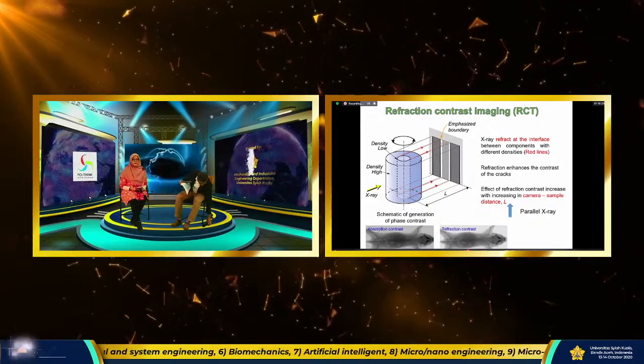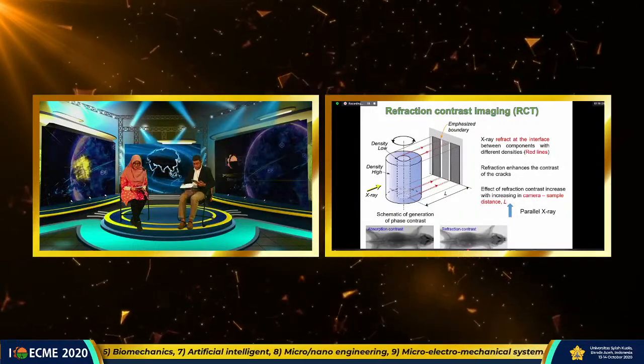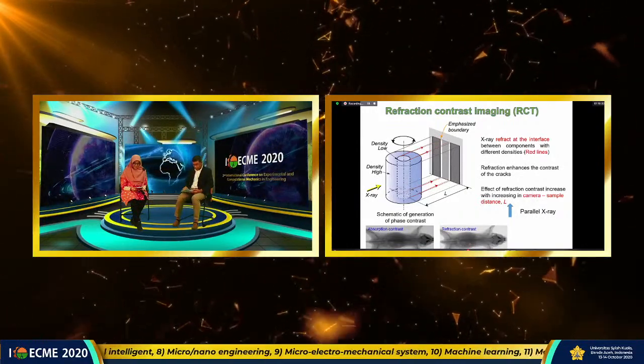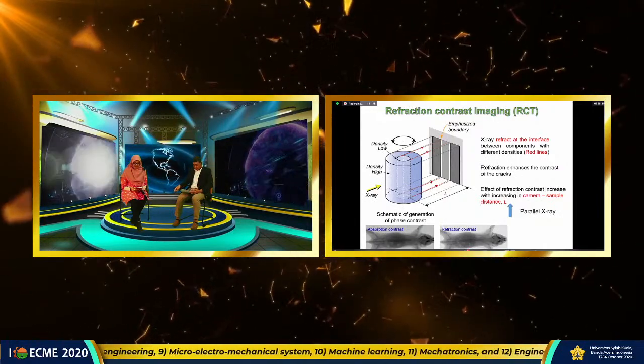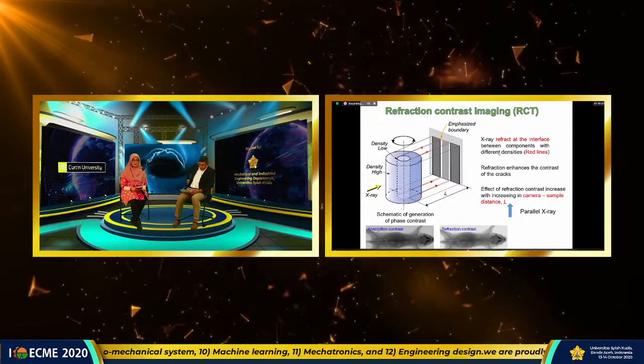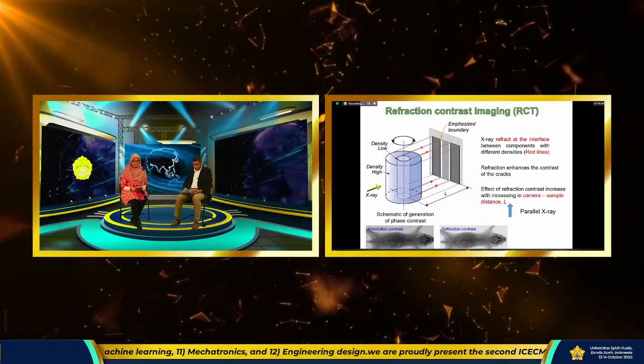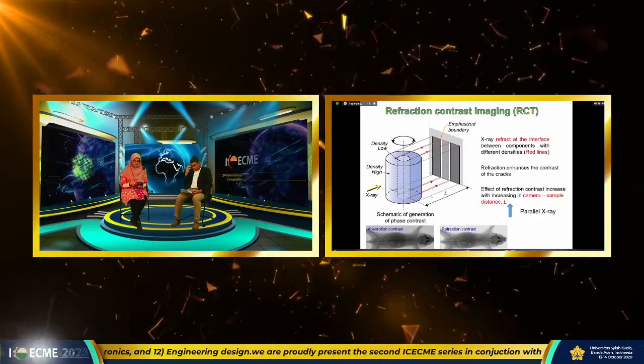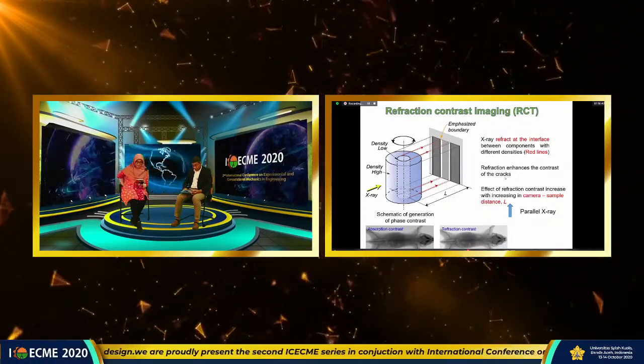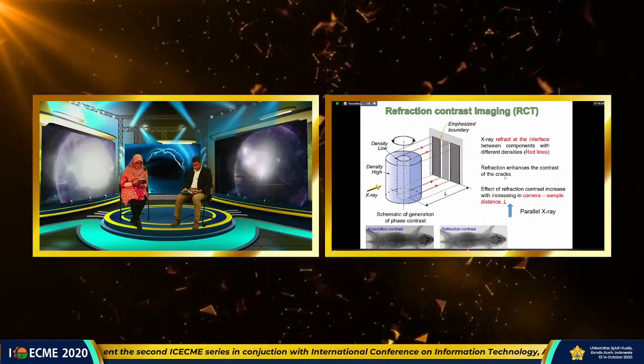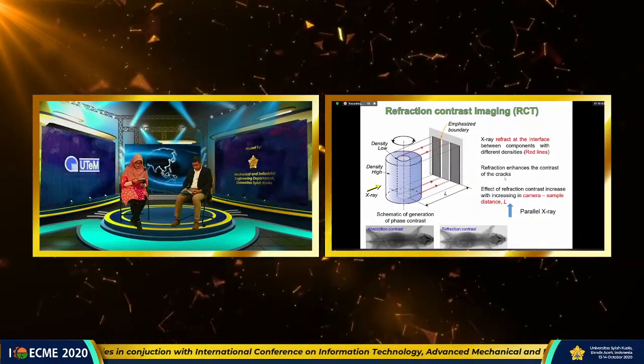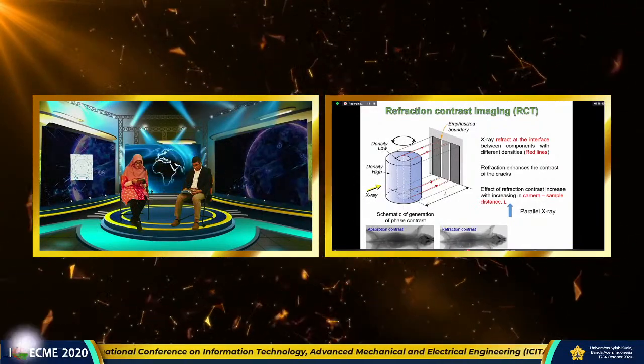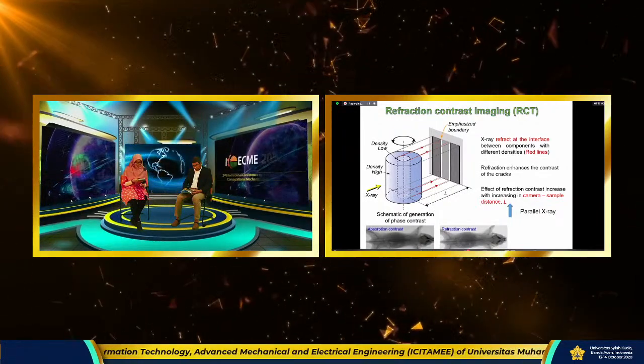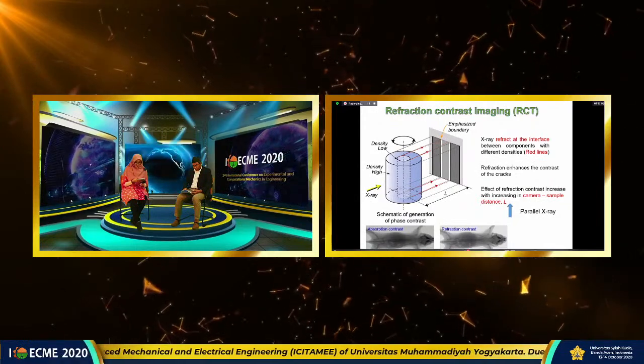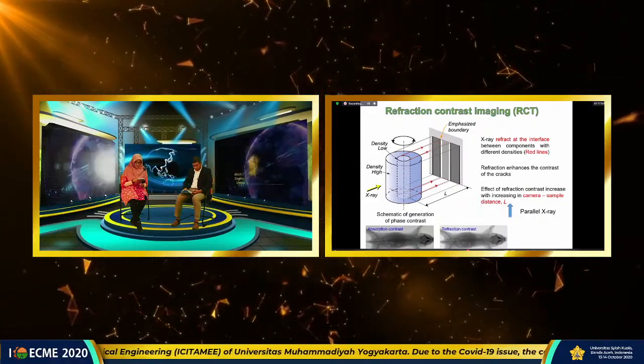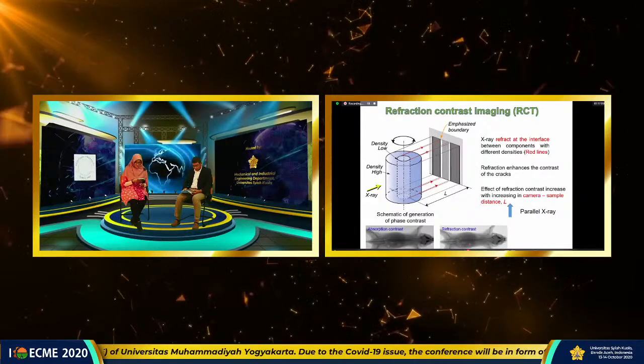In this region, the refracted beam and the direct beams are superposed. So we can enhance the contrast of the boundary between two materials. It's also used to observe cracks with very small opening displacement. The effect of refraction contrast increases with increasing camera-sample distance. It means that no special devices are required. A normal CT system is enough for this contrast.